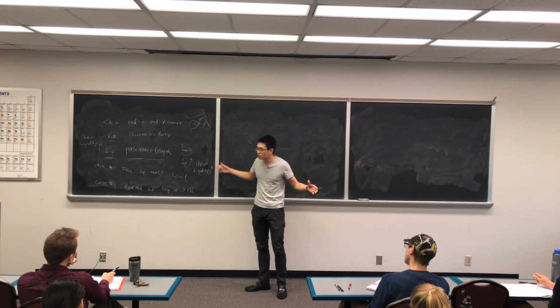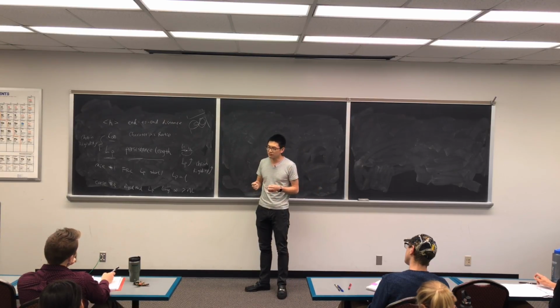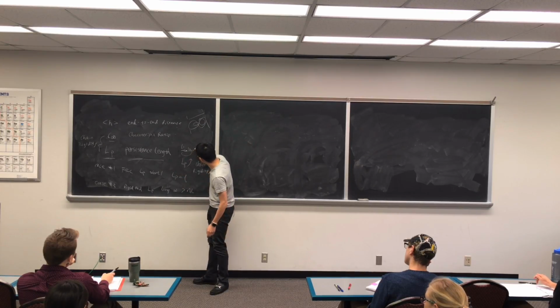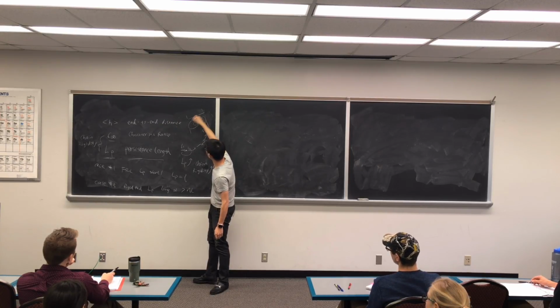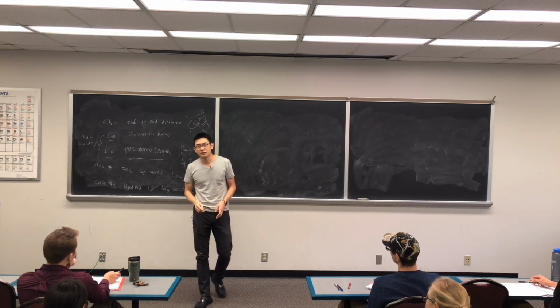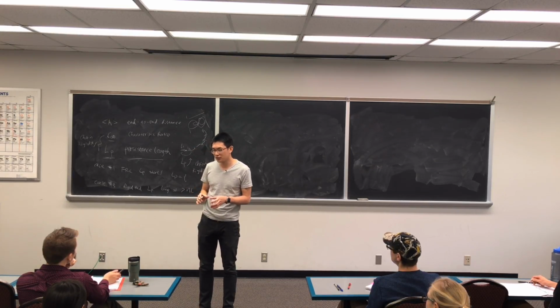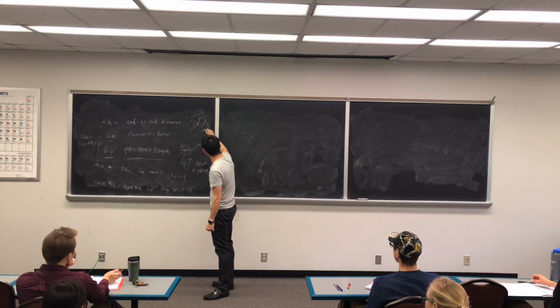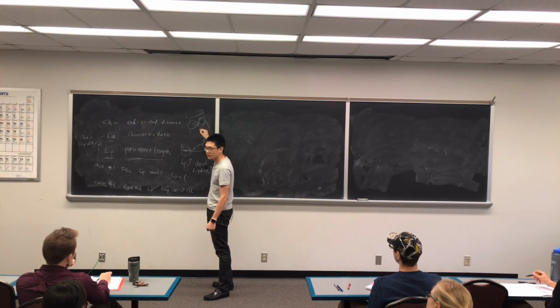Before I jump into that, there's a direct, very physical way you can understand the persistence length. While you walk along the chain, it will go this way, a lot of things, then it will finally bend over. So the persistence length has a very interesting physical meaning: it is when your bond bends at 90 degrees. What distance it takes to bend 90 degrees. So, for example, if it takes this much bond to bend 90 degrees, then that's the definition of the persistence length.